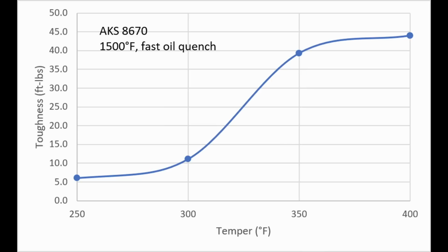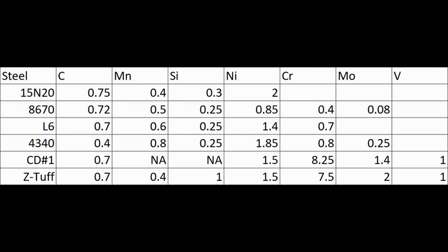We didn't go out to 450 to see if tempered martensite embrittlement also is seen at 450 degrees. But overall, the steel is looking pretty similar to the 15N20, even though the 8670 does have lower nickel than 15N20, about half as much.